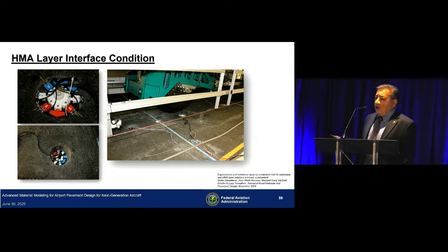We are looking at other kinds of instrumentation. One of the distresses we see on airports, once the tire pressure of the aircraft went high, was delamination in the asphalt layers at high-speed exits. So our French counterpart, DGAC, and their research group called STAC, have worked with Gustave Eiffel University to develop this device called the ovalization device. With this device, you basically take out an asphalt core, install it right above the interface and right below the interface, and then you measure responses in the three principal directions.